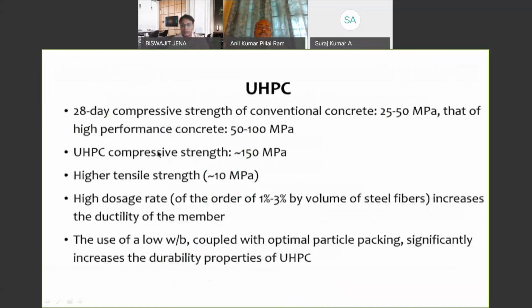So we have conventional concretes that typically have a strength of 20 to 25 megapascal, and up to 50 megapascal for high performance concrete, and you can also go up to 100 megapascal in that case. But ultra high performance concrete is designed with a compressive strength of 150 megapascal. They are also designed for high tensile strength of about 10 megapascal. And you can achieve this by extremely dense packing of particles, by making the microstructure so dense that the particles are so close to each other, and stresses are transferred very nicely.